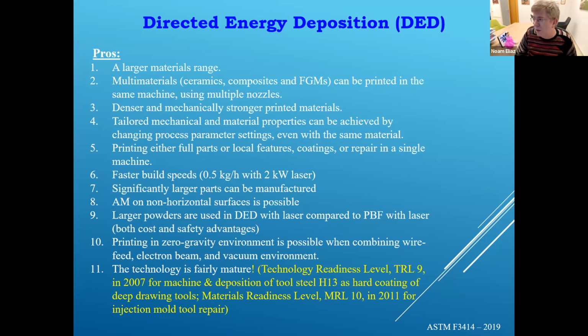You can tailor the mechanical and material properties locally. You can do either full parts or coatings or repair in a single machine. Note the fast build speeds. You will see very large parts that are being printed using the DED. I mentioned here a 2 kilowatt laser simply because this is the laser that I have at Tel Aviv, an IPG fiber laser. In my case, there are some inventions or new technologies there that are relevant. I can touch on it later.